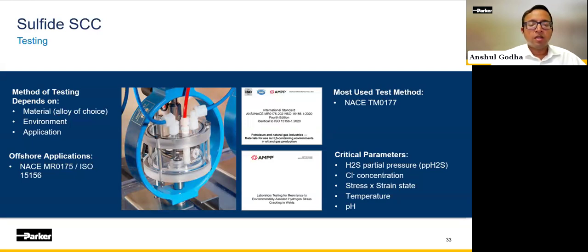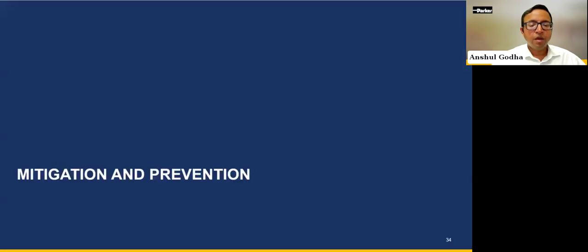In these standards, there is a lot of detail, and they define very well the critical parameters such as hydrogen sulfide partial pressure, chloride concentration, stress-strain state, different temperatures, as well as different pH of the solutions. So based on the application and the choice of our parameters, the test can be conducted as needed. Next, I'll hand over to Paula to talk about some of the mitigation and prevention issues related to stress cracking.